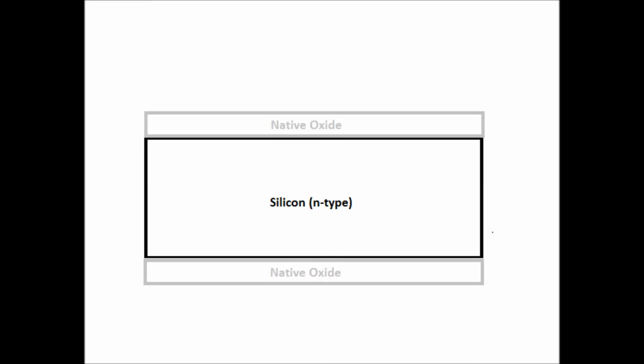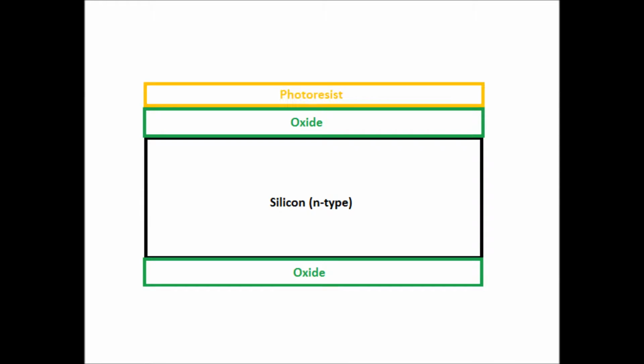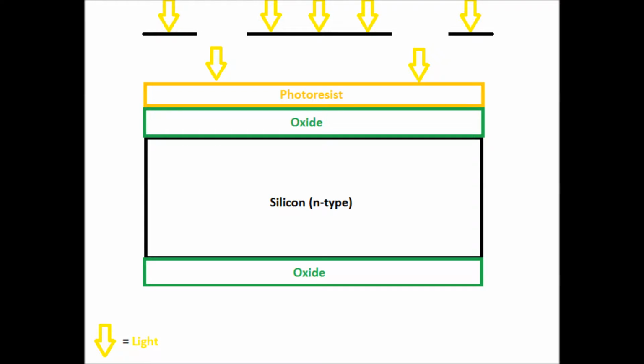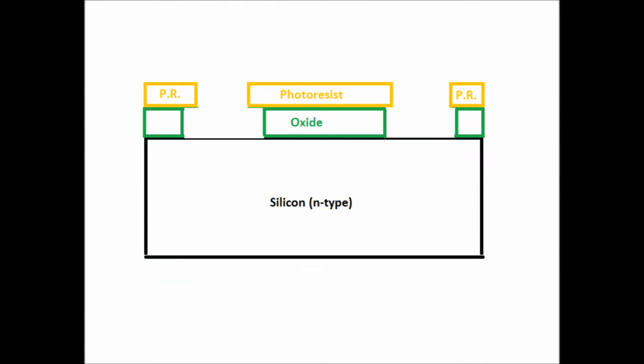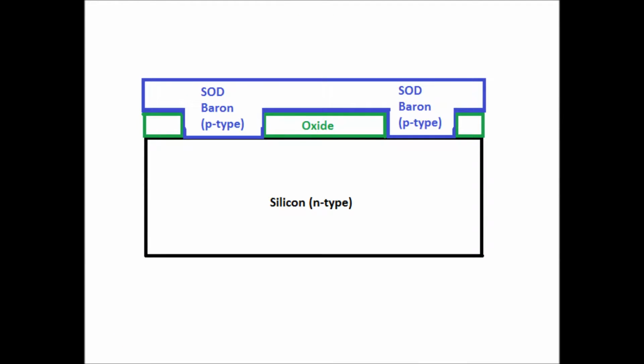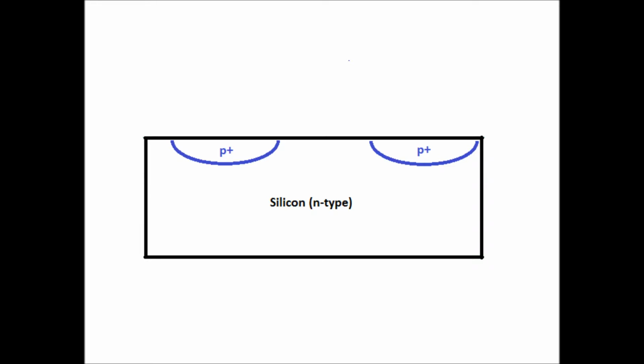The ideal process was to take a new wafer, RCA clean, grow an oxide layer, spin on photoresist, photolithography, develop, BOE, spin on dopant, and predeposition to get nicely doped layers. In actuality, this is not what happened.